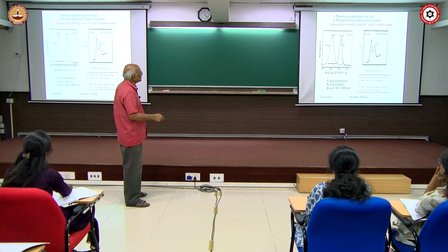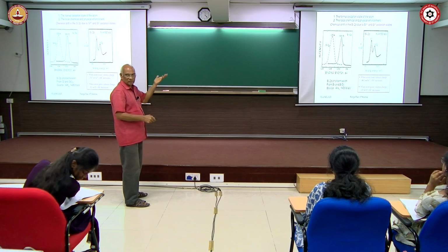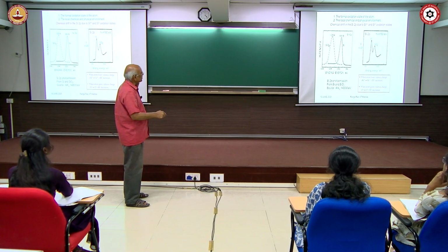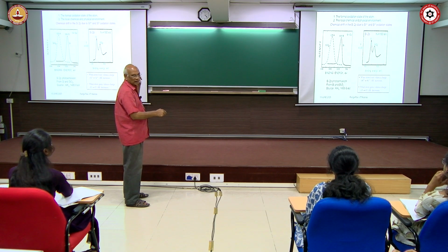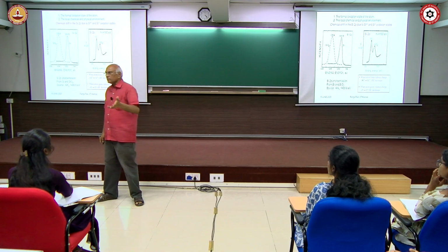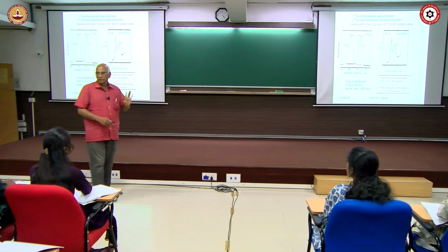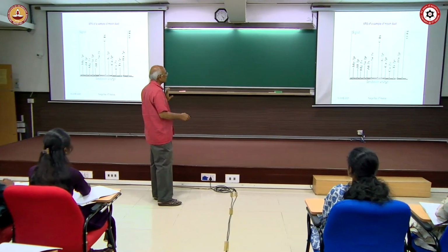Okay, you can see here also silicon and SiO2. Pure silicon will give you a peak around 99.15 electron volt, but the moment you oxidize it to silicon 4 plus, it changes, about 4 electron volt difference is there. Silicon 4 plus has a higher binding energy. So, by looking at this, you can easily identify the oxidation state. That is possible.